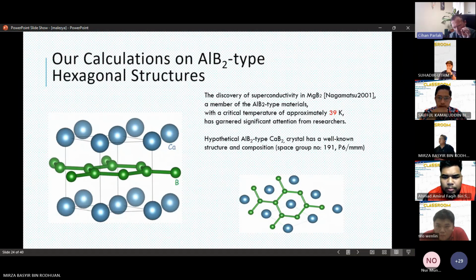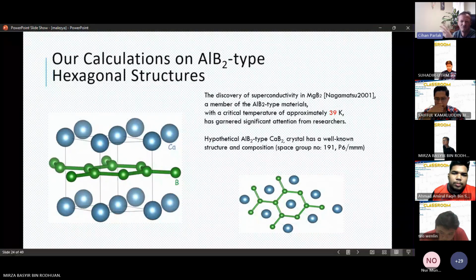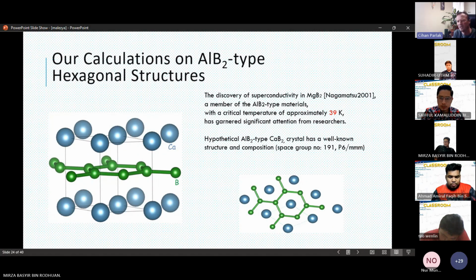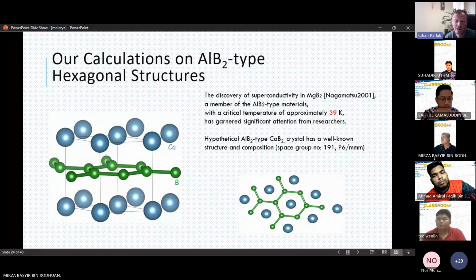If you want to find any new superconductor in this hexagonal form, you can change the magnesium, or you can change the borons, like gallium and so on. A lot of studies on this aluminum diboride type of materials are already published. And why did I choose calcium diboride? Calcium diboride is still hypothetical. There are no experimental results on calcium diboride, and it can also crystallize in the aluminum diboride structure.